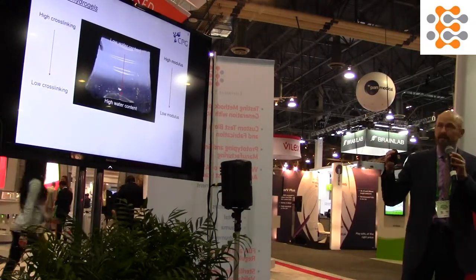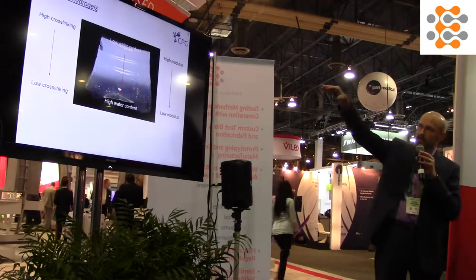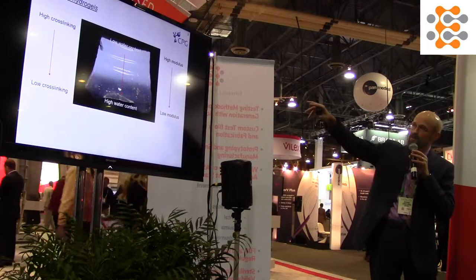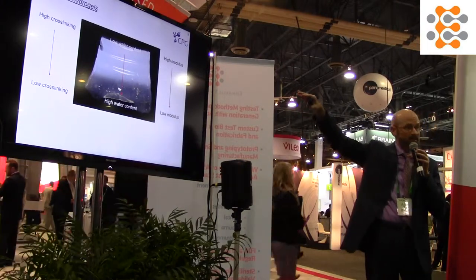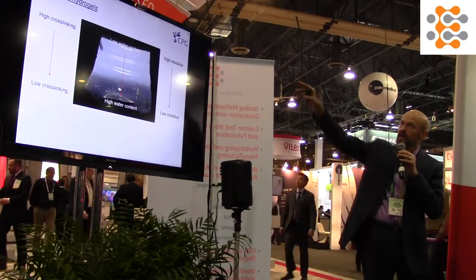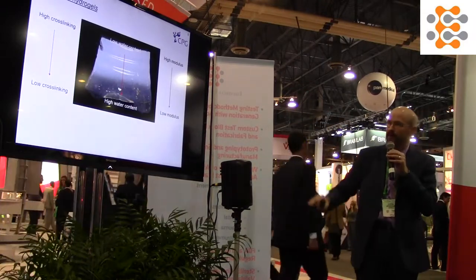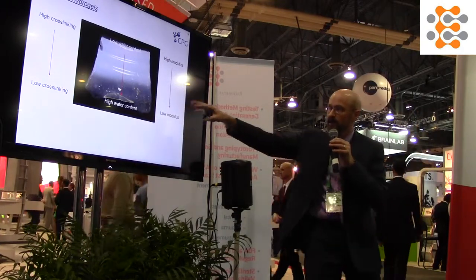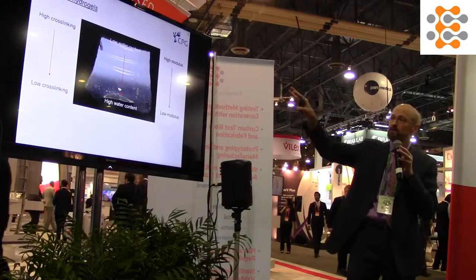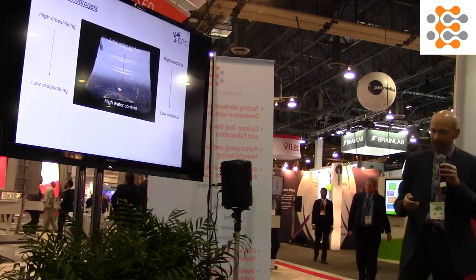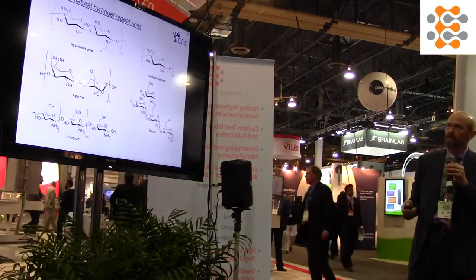This is an example of a hydrogel that we made where we introduced a gradient, with high cross-linking on the upper end and very low cross-linking on the lower end. What that results in is very low water content on the upper end, high water content on the lower end, and commensurately high modulus and low modulus. So this would be a nice example of a material that may be very lubricious down here and compliant, whereas down here where you may want to anchor it to the bone, it's going to be much more rigid with better mechanical properties.